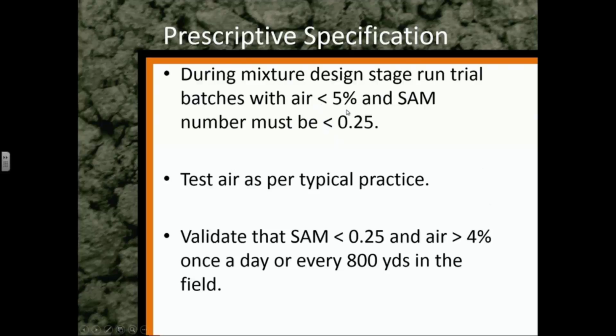You say, why would you do that, Tyler? Well, you're forcing them to have a lower air volume. And you're making sure that at that time they use a lower air volume, that they get a SAM number of 0.25. So what you're doing is you're checking, I'm going to make sure I'm on the bottom end of the spec, and I'm going to make sure my SAM number is pretty good. Hey, and you can change these numbers to be whatever you want. But as long as my SAM number is less than 0.25 and I'm near the bottom of my spec, I'm happy and I'm good. And being near the bottom of the spec is very important.